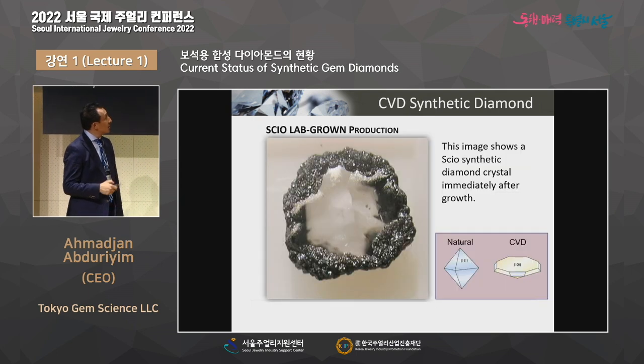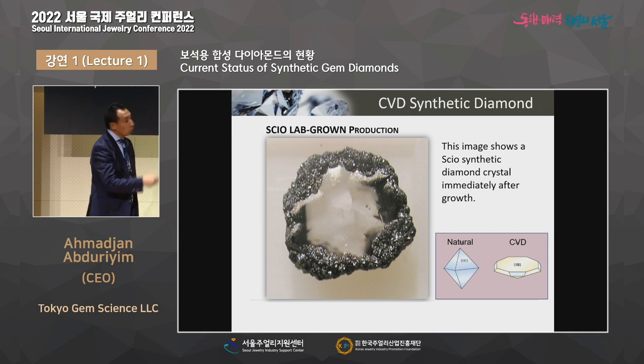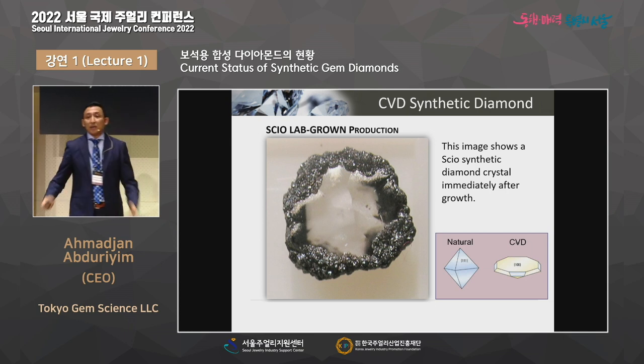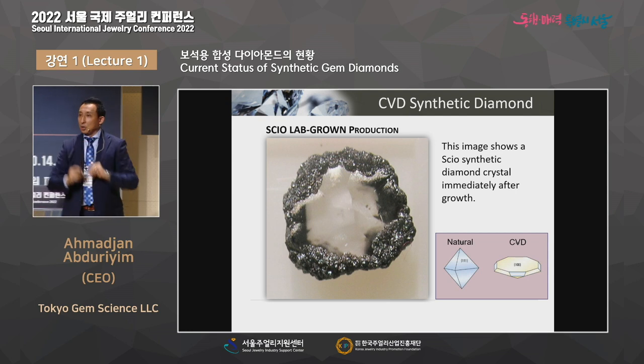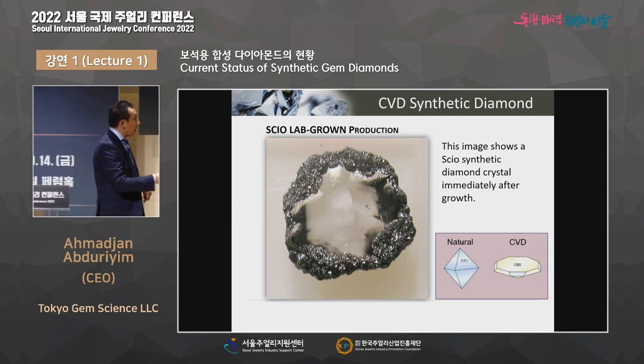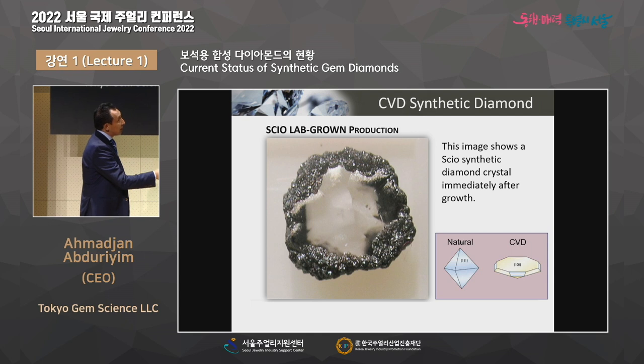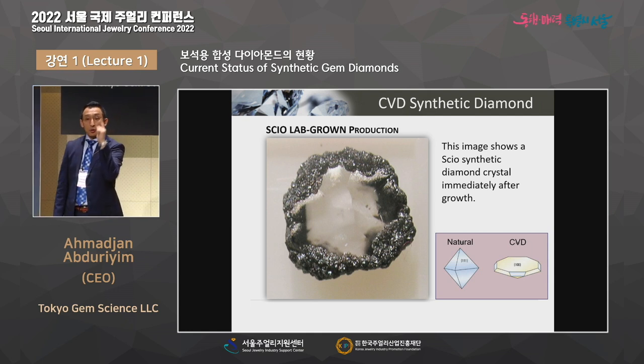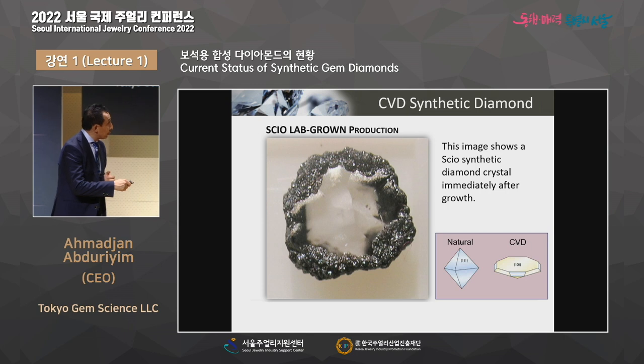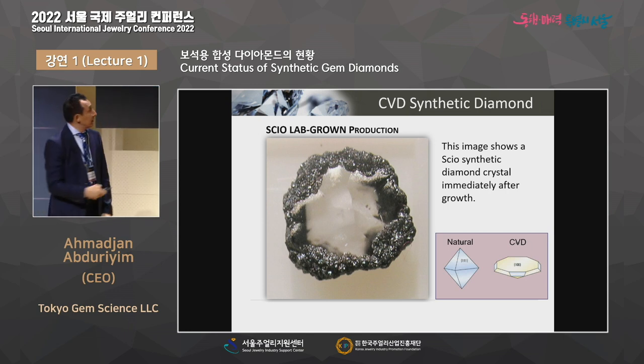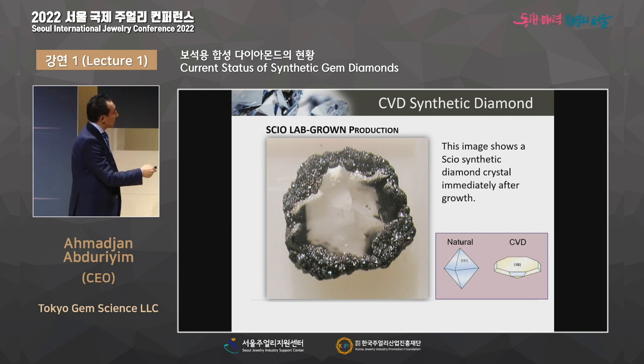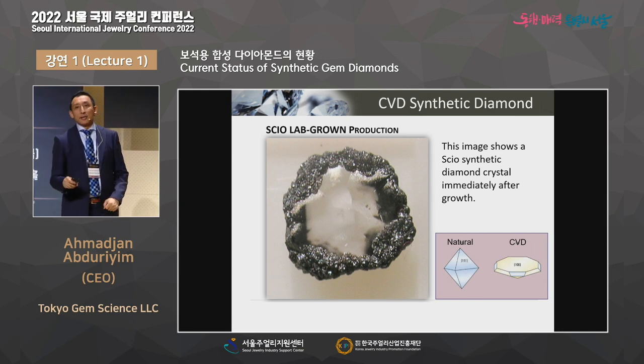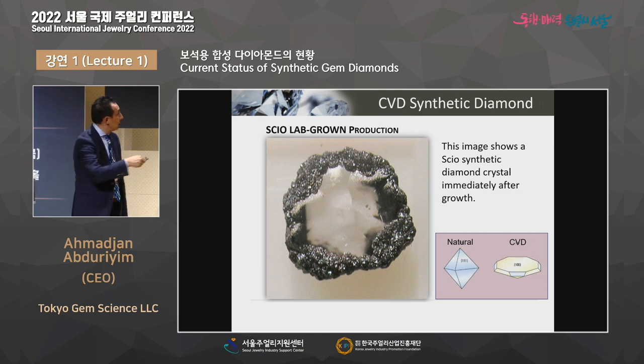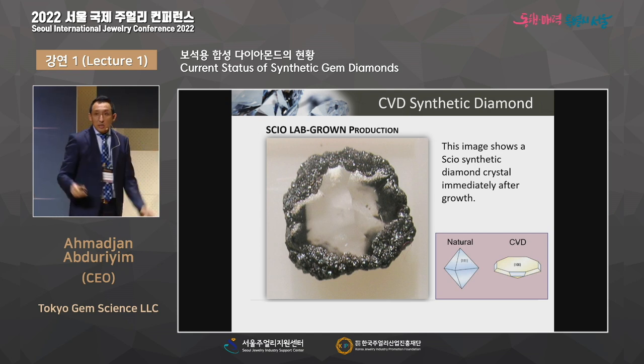And after that, the shape is like this. Normally, the natural diamond, as I mentioned before, is an octahedron. Most diamonds have this shape. However, the CVD diamond grows starting from the 001 face. It's not from the 111 face. It's totally different. So that's why it's flat, like that. And you will see here, it says nano polycrystalline. Small diamonds get together in this area, and in the center, it becomes a very clean single crystal.